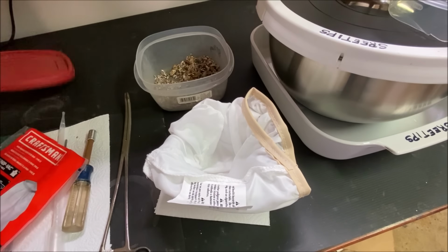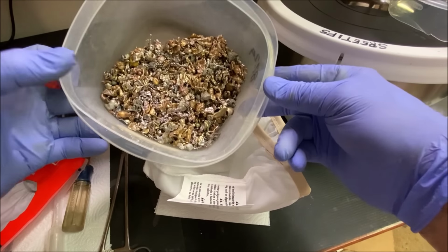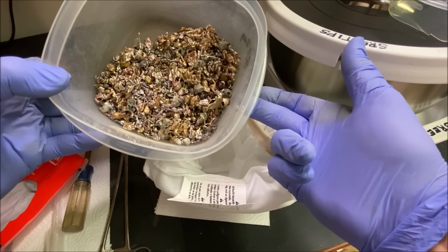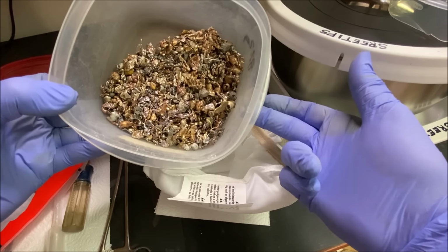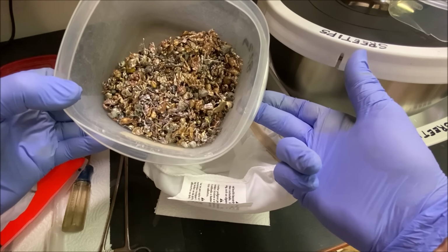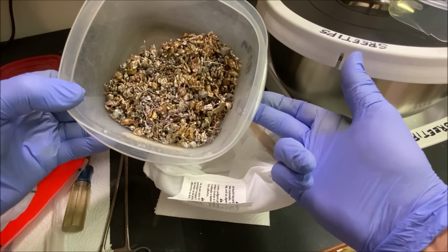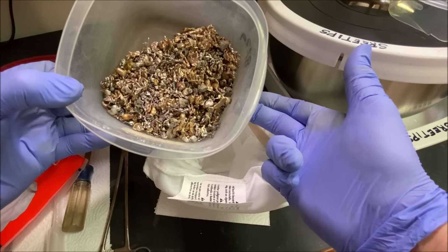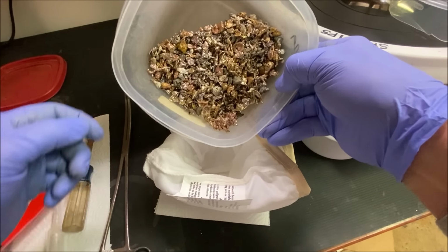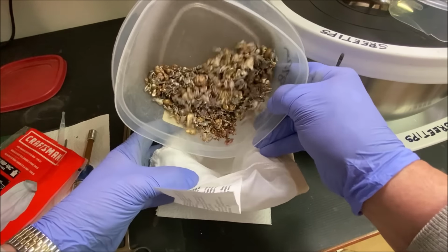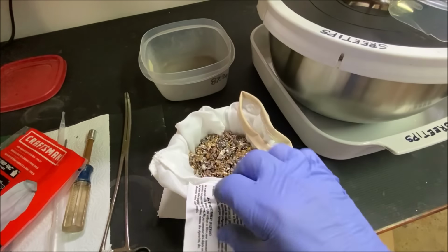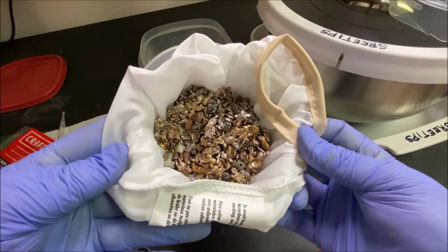Here's our impure silver shot that we're going to refine. This is cement silver that's been melted into these granules. I get this from my gold refining. I use sterling silver to refine gold. Then I recover the silver from that and form these granules. And this is about 98% impure silver. I'm going to dump it right on in here. That's probably about a kilo or so, maybe 700 grams, I guess, of impure silver down in the anode filter basket.